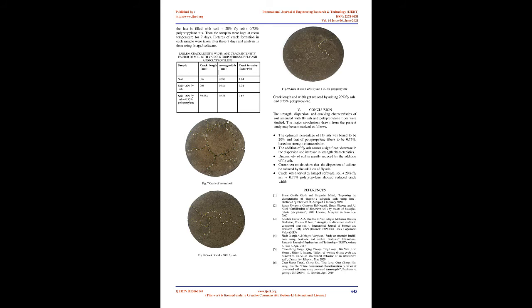V. Conclusion: the strength, dispersion, and cracking characteristics of soil amended with fly ash and polypropylene fiber were studied. The major conclusions drawn from the present study may be summarized as follows. The optimum percentage of fly ash was found to be 20% and that of polypropylene fibers to be 0.75%, based on strength characteristics. The addition of fly ash causes a significant decrease in the dispersion and increase in strength characteristics. Dispersivity of soil is greatly reduced by the addition of fly ash. Crumb test results show that the dispersion of soil can be reduced by the addition of fly ash. Crack when tested by ImageJ software, soil plus 20% fly ash plus 0.75% polypropylene showed reduced crack width.